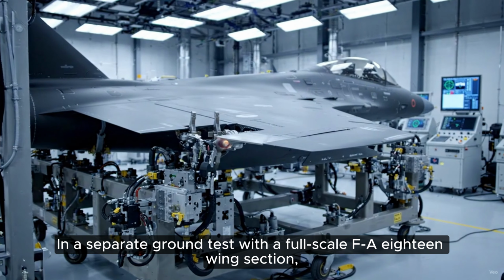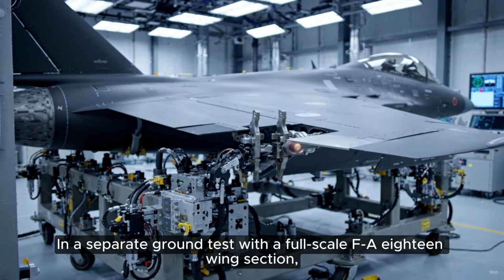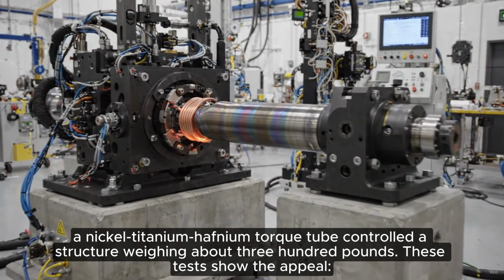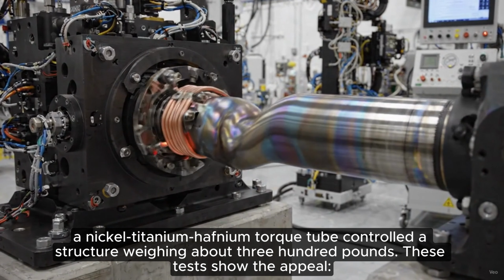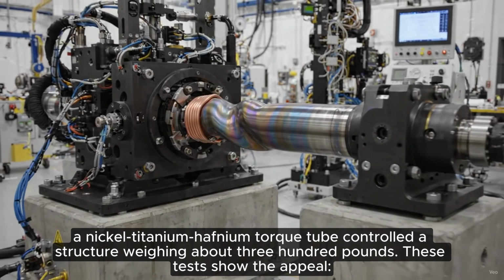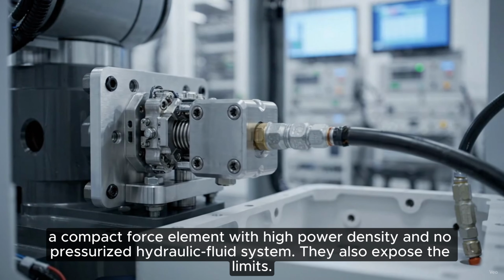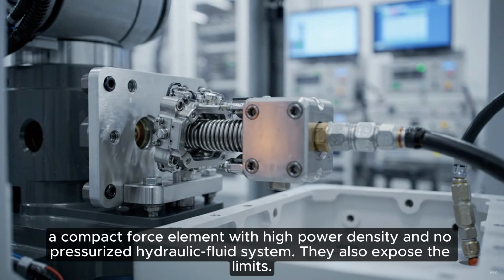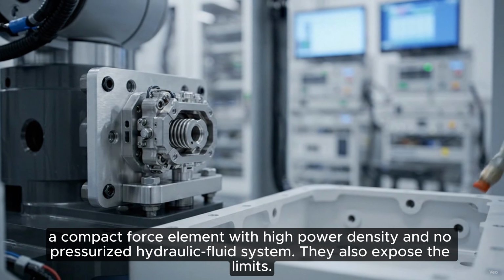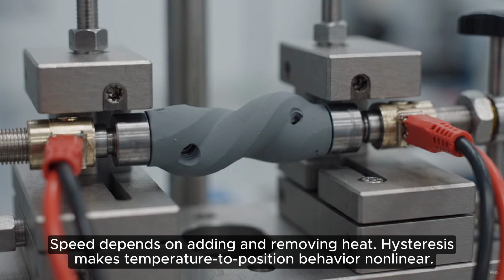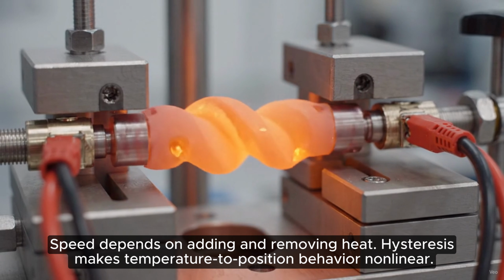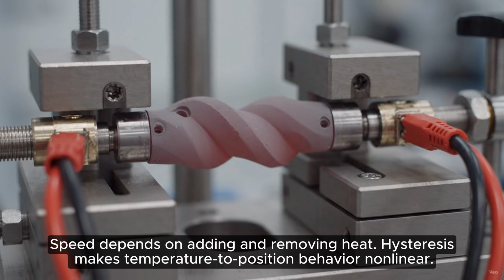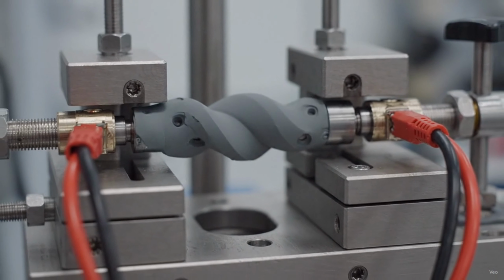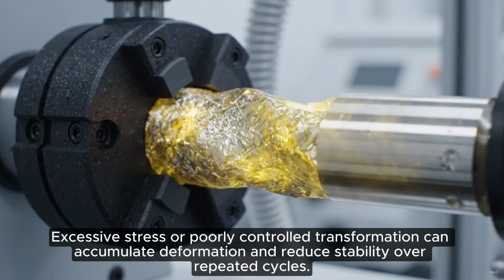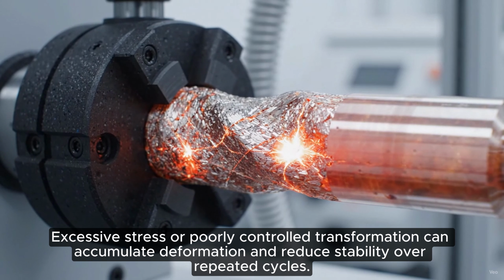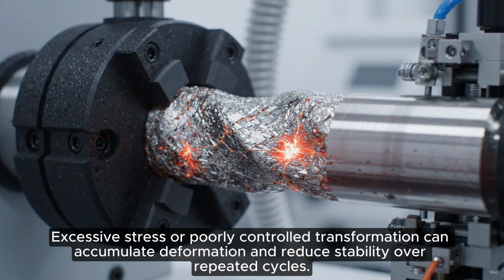In a separate ground test with a full-scale FA-18 wing section, a nickel-titanium hafnium torque tube controlled a structure weighing about 300 pounds. These tests show the appeal: a compact force element with high power density, and no pressurized hydraulic fluid system. They also expose the limits. Speed depends on adding and removing heat. Hysteresis makes temperature to position behavior non-linear. Excessive stress or poorly controlled transformation can accumulate deformation and reduce stability over repeated cycles.